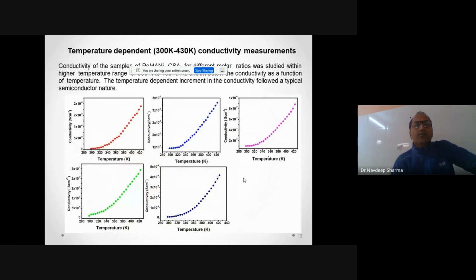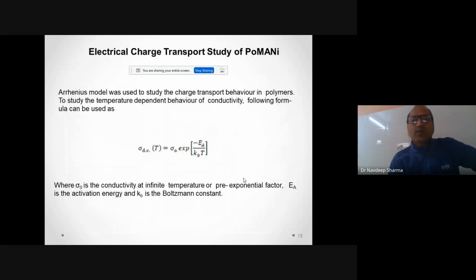And the temperature dependent conductivity is done at 300 to 430 Kelvin. The conductivity shows exponential behavior, and this behavior is very useful for the further study of electrical charge transport exploration of poly(ortho-methyl aniline), that is, how the conductivity in the polymer is going on by the movement of charge carriers in them.